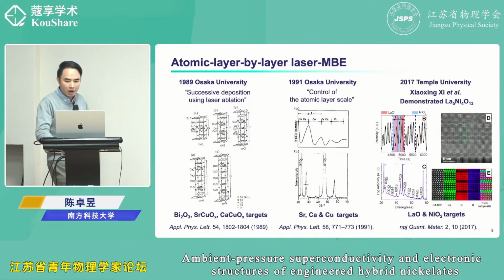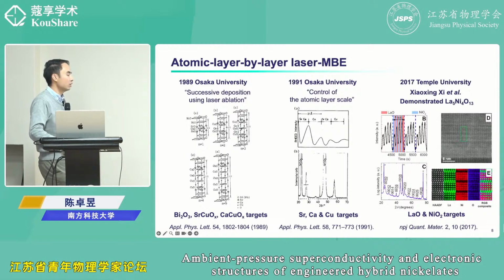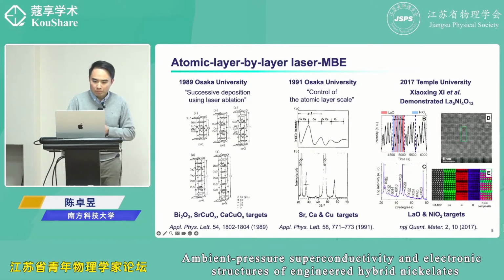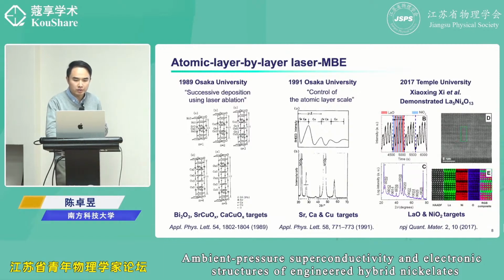Another route that's not so mainstream is to use different targets to do this similar PLD stuff. Someone called it atomic layer by layer laser MBE. This technique can be dated back to the late 80s when the cuprates were just discovered. So they use different targets, for example, bismuth oxide, strontium copper oxide, calcium copper oxide, and successive deposition using this laser ablation, they can control the structure of BSCCO. And more recently, this is also applied to the nickelates in the last decade. Xi Xiaoxing from Temple University can also grow pretty good